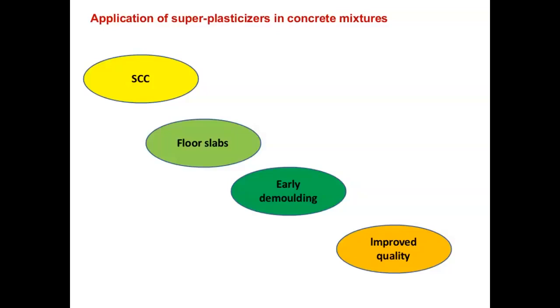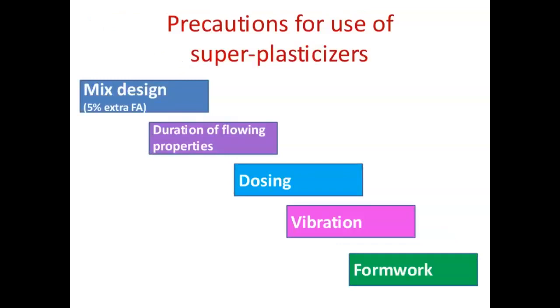For example, self-compacting concrete, floor slab for early removal of formwork, and for improved work quality, we can go for these superplasticizers. Then we have to take some precautions while using superplasticizer. As I said, for mix design, since we are reducing some quantity of water and cement, we can add some 5% extra fine aggregate. And regarding flowing property, when you use superplasticizer, it will lose its flowing property after some time. So within 30 to 45 minutes, that concrete should be used. Otherwise, while going with ready mix concrete or other things, 5 to 10 minutes before placing, we can add superplasticizer. And also, after adding superplasticizer, continuous mixing for 5 minutes will improve the workability.